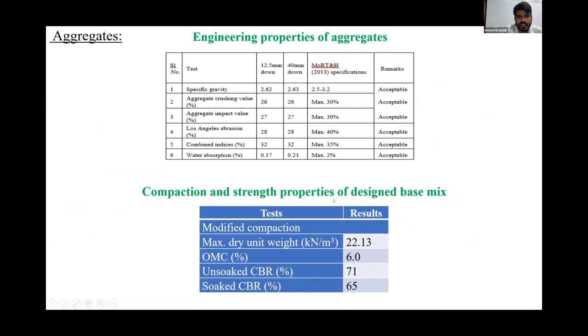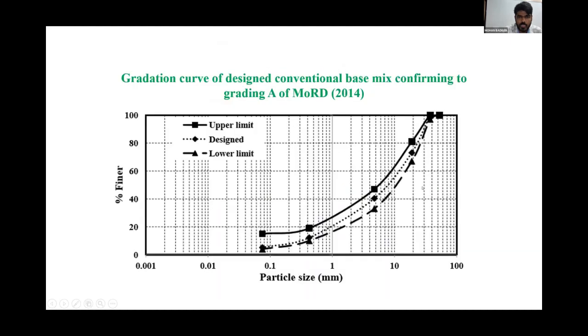Aggregates. Aggregates are used to prepare the conventional base mix, and the various aggregate properties were determined as per the IS 2386 standards. From the table, it is observed that all the aggregate properties are acceptable. And compaction and strength properties of the design base mix: the design base mix possesses a maximum dry unit weight of 22.13 and OMC of 6%. It has a soaked CBR value of 65%.